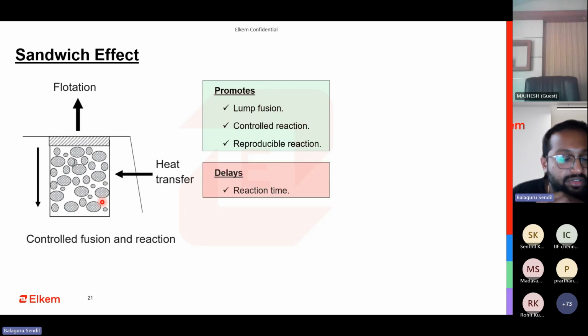Unfortunately, if there is some mismatch, then you will have a reaction delay. What I'm trying to say here is that if the sandwich is properly made, you will have the reaction time very slow. You can simply have a process control. Once you start tapping, you can see at what time the reaction starts. The start of reaction should always happen at least 30-40 seconds in. If you're tapping for a minute, the start of reaction should always happen somewhere between 40 to 50 seconds. And the end of reaction should always happen after you finish tapping.